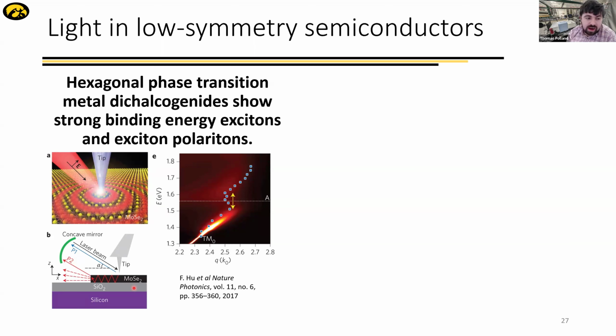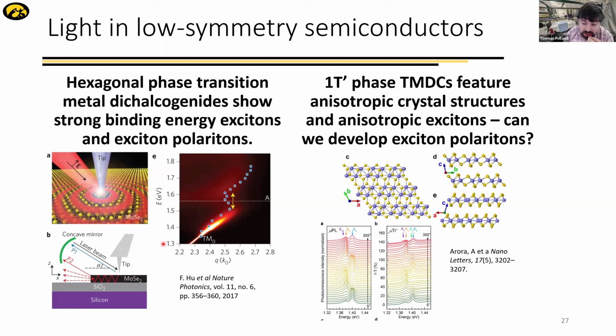Now, MoS2 and the other conventional TMDCs have this hexagonal structure. And we just talked about molybdenum trioxide, which has this orthorhombic crystal structure, which gives some extra unusual properties because of its anisotropy. So the question is, are there any highly in-plane anisotropic transition metal dichalcogenides? And the answer is yes, there's rhenium diselenide.